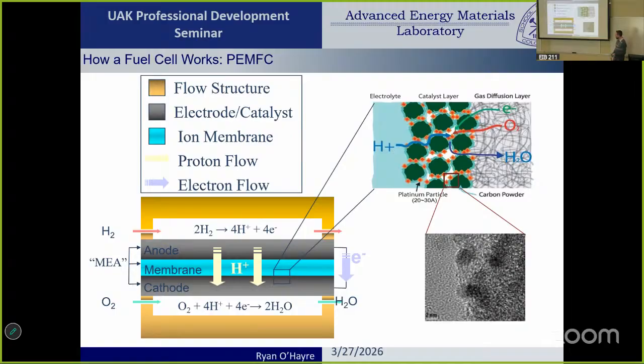So, all right, if you use a powerful microscope, like a transmission electron microscope that can see almost at the atomic level, you can zoom in on one of those carbon platinum catalyst structures. And so here is a TEM image. I don't know how well you can see this with the lights, but that scale bar there is 2 nanometers. So an atom is like 0.2 nanometers. So that's about 20 atoms. That scale bar is about 20 atoms.